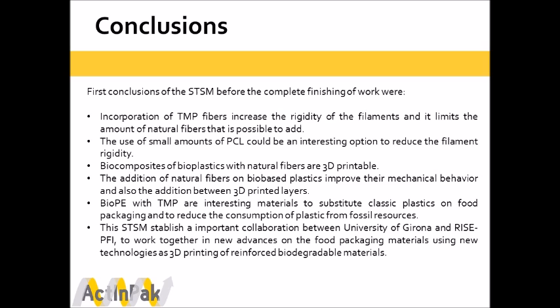First conclusions of the short-term scientific mission, before the complete finishing of the work. Incorporation of TMP fibers increases the rigidity of the filaments, and it limits the amount of natural fibers that is possible to add. The use of small amounts of PCL could be an interesting option to reduce the filament rigidity. Biocomposites of bioplastics with natural fibers are 3D printable. The addition of natural fibers to bio-based plastic improves their mechanical behavior and also the adhesion between 3D printed layers.